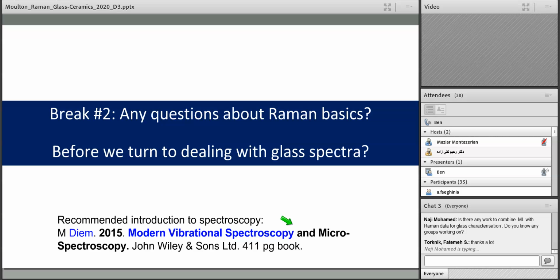But with that being said, I highly recommend, if you're working with glasses, to avoid this at all costs because there's a lot of covariance in the peaks. There's a lot of peak overlap. And so machine learning, if we don't know those physically realistic values, is not going to be able to tell us because of the covariance and all the peak parameters that are produced in these broad spectral features in glass. So with that caveat, machine learning is the future. Max Diem gives a pretty good introduction.